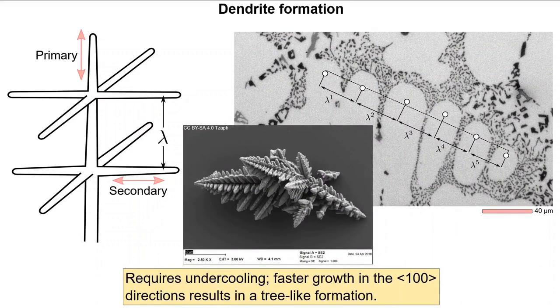Again, it's important to highlight that this goes on in three dimensions, even for pure metals, as depicted here for a dendritic cell made from pure copper. The intervening space between the dendritic structure is usually filled in with a secondary phase that forms. In the case of the cast aluminium alloy, it could be considered a binary eutectic system of aluminium and silicon. The dendrites are a primary aluminium-rich phase, and the interdendritic region is populated by a silicon-rich phase. Predicting the length scale of dendritic microstructure is non-trivial. As you can see, the secondary arm spacing of the aluminium alloy is 40 micron, while the scale bar for the inset copper micrograph is 10 microns. We'll discuss microstructure morphology further in subsequent lectures, but what we have is what we need to examine a typical cast-ingot microstructure.